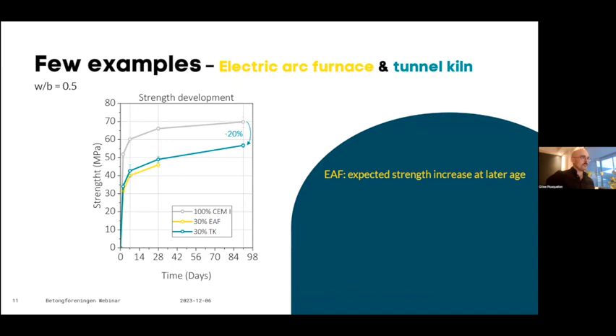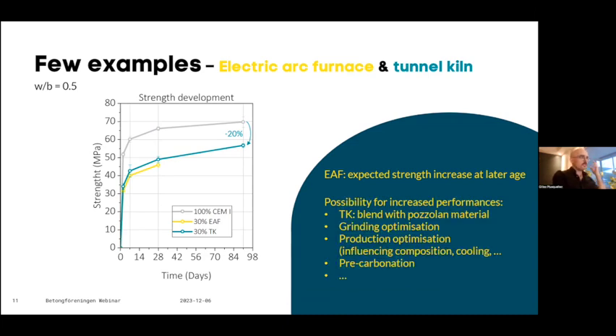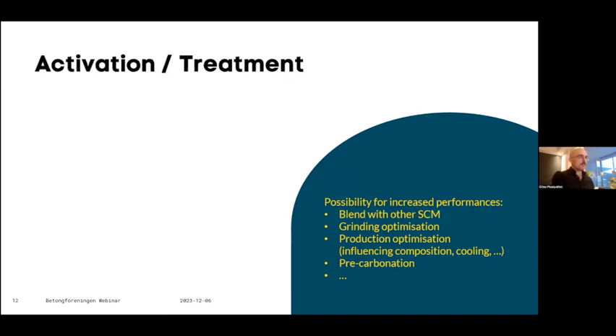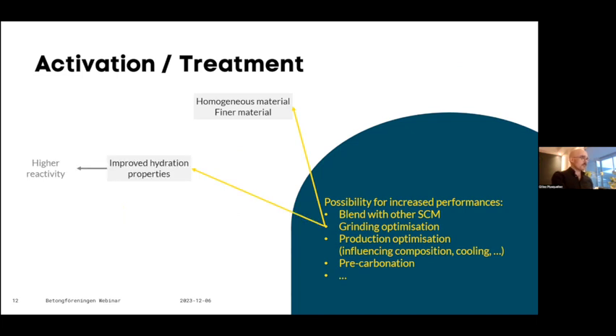Although I think it's not an extraordinarily good result, this was obtained using the material raw, without any treatment or pre-treatment whatsoever. So this could actually be improved quite a bit. There are many possibilities for that. In this specific case of the tunnel kiln, one possibility would be to mix it with a pozzolan material because of all the Portlandite that was formed or already present from the beginning. It is also possible to do a grinding activation, which leads to a more homogeneous, finer material, which will be more reactive and therefore have improved hydration properties.